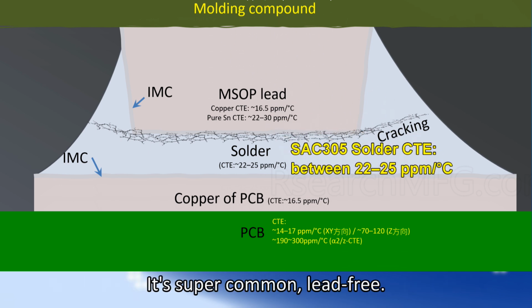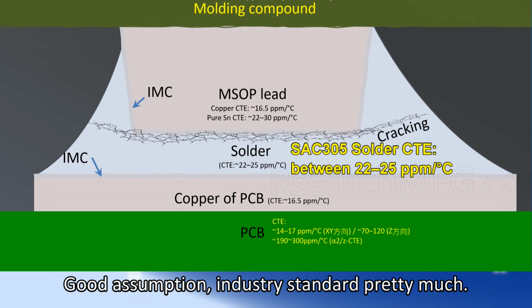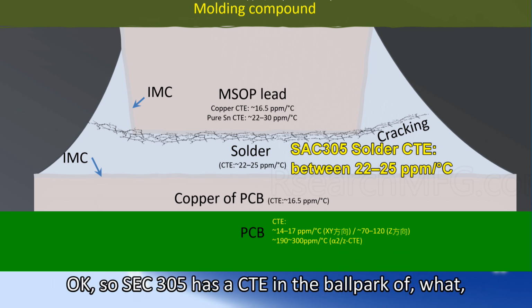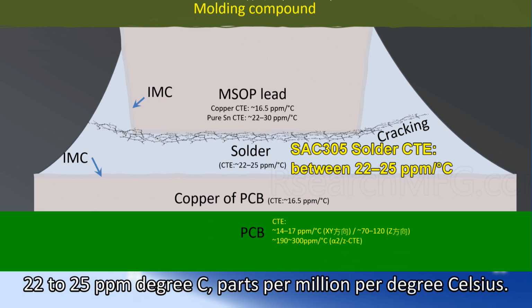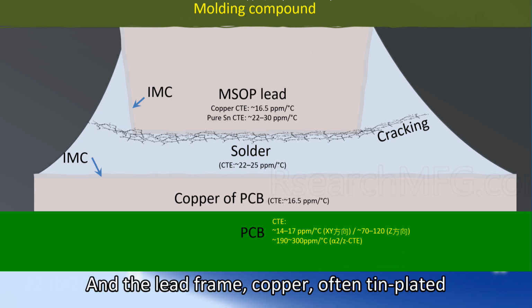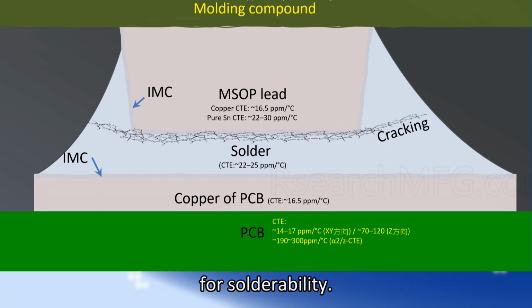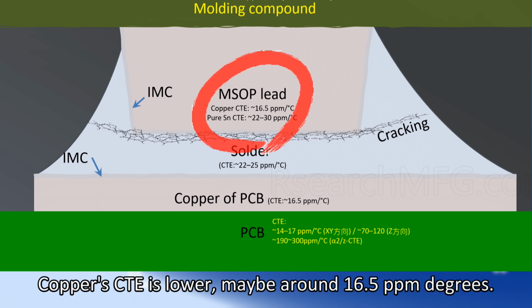It's super common, lead-free. Good assumption, industry standard pretty much. Okay, so SAC305 has a CTE in the ballpark of 22 to 25 ppm per degree C, parts per million per degree Celsius. Around there, yeah. And the lead frame, copper, often tin-plated for solderability. Copper's CTE is lower, maybe around 16.5 ppm per degree.